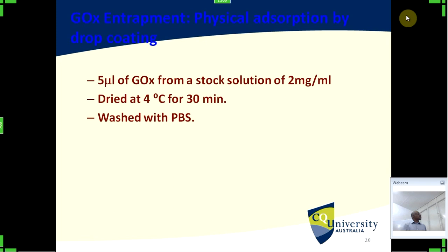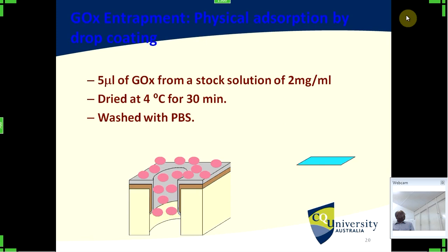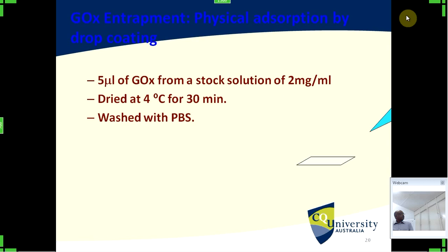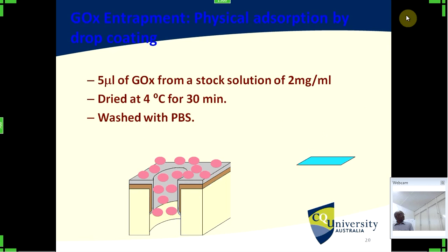Glucose oxidase entrapment was first done by physical deposition. We just drop them, 2 milligram per milliliter, onto this one, dried at 4 degrees centigrade for 30 minutes, and washed in phosphate buffer solution, and it worked fine.